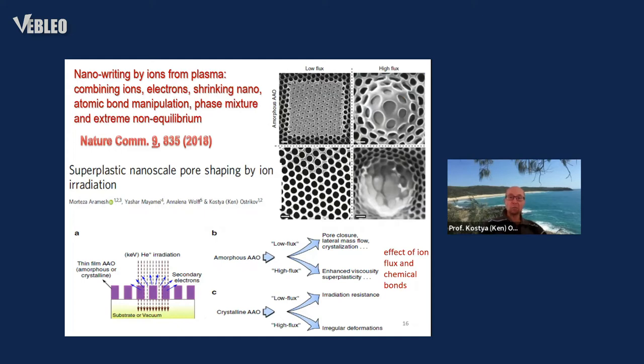If we extract ions from the plasma, which is very common in ion sources and also in materials characterization analytical devices, such as the helium ion microscope. When we extract the ions, then the control of energy of those ions, as I said, is very important. But another very important factor that needs to be controlled during the interaction of ions with matter is the ion flux. So when the ion flux is controlled, when helium plus ions are extracted and irradiated onto porous alumina templates, the effect of the flux of helium ions ejected by the helium ion microscope turned out to be very, very important. And the pores that are intrinsic to this porous material become shrinking.